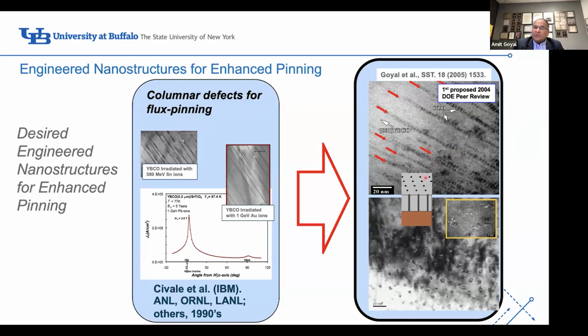And when you look down the film or the C-axis, you see a structure like this. These are nanocolumns of barium zirconate. And now you can start to see this starts to resemble a Swiss cheese microstructure again. These are about 5 to 10 nanometers in diameter and about 5 to 10 nanometers in separation.